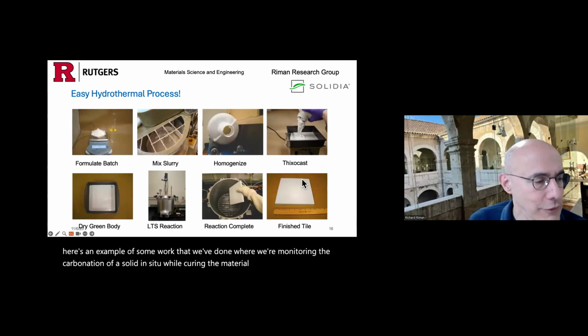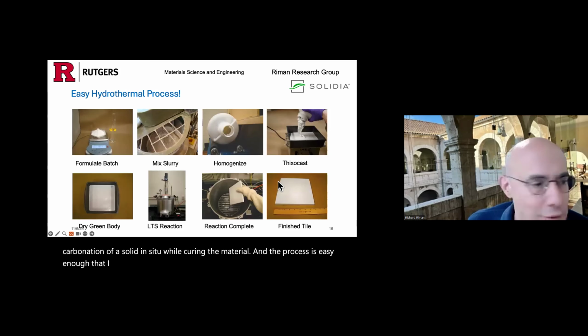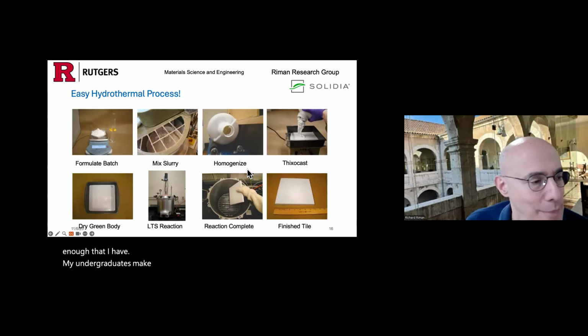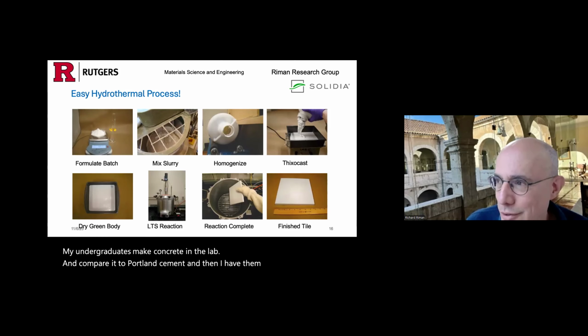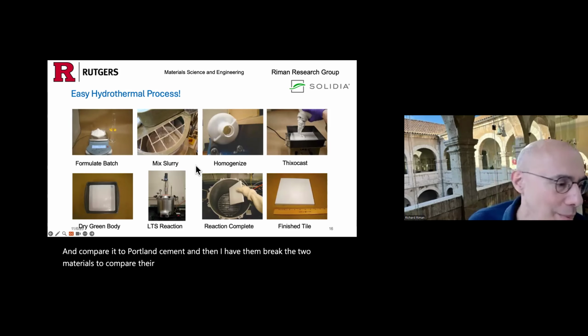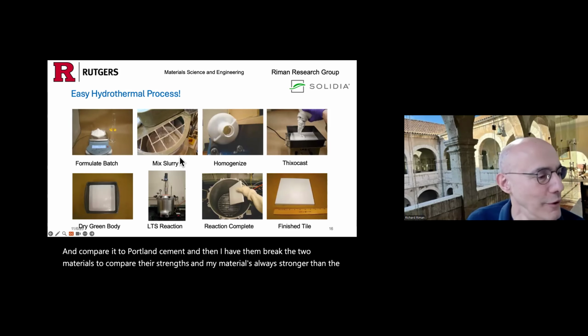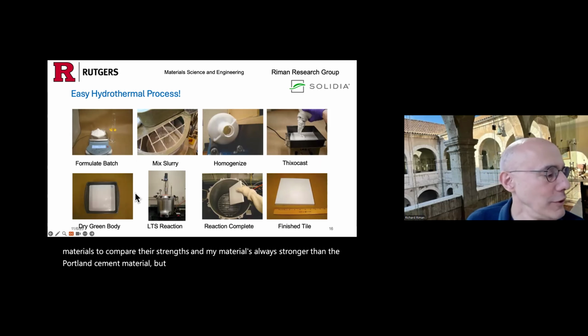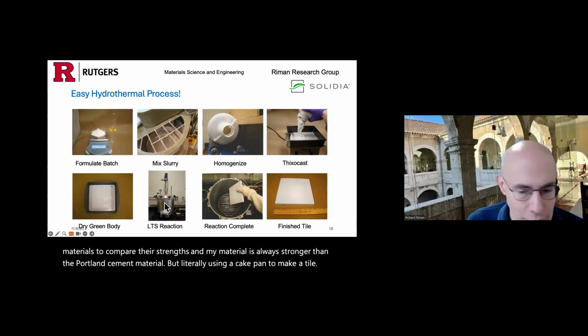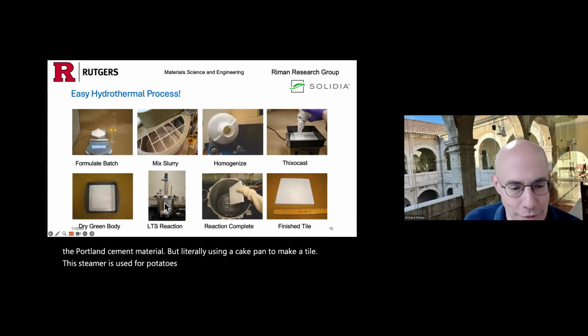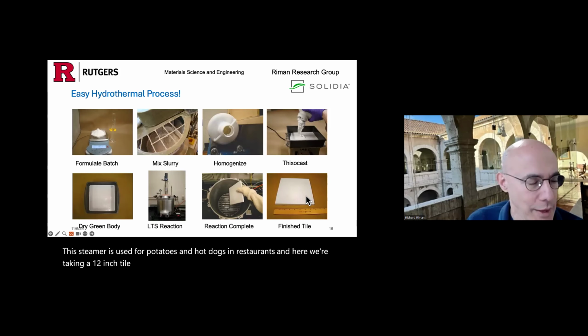And the process is easy enough that I have my undergraduates make concrete in the lab and compare it to Portland cement. And then I have them break the two materials to compare their strengths. And my material is always stronger than the Portland cement material. But literally using a cake pan to make a tile, this steamer is used for potatoes and hot dogs in restaurants. And here we're taking a 12-inch tile out. And they're beautiful looking materials on top of that because calcium carbonate gives materials a white appearance.